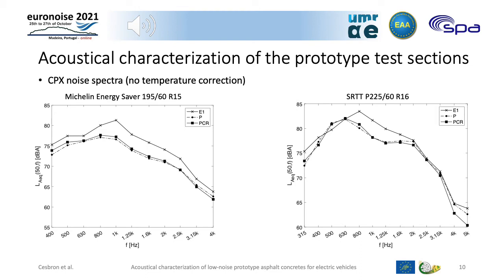For both tire models, the prototype test sections P and PCR have very similar spectral shapes. The maximum spectral value for P and PCR is observed at 800 Hz for the Michelin tires and at 630 Hz for the SRTT tires. By comparison with E1, the highest noise reduction is obtained in the frequency range between 800 Hz and 2000 Hz, with a maximum of about 4 dBA at 1000 Hz.